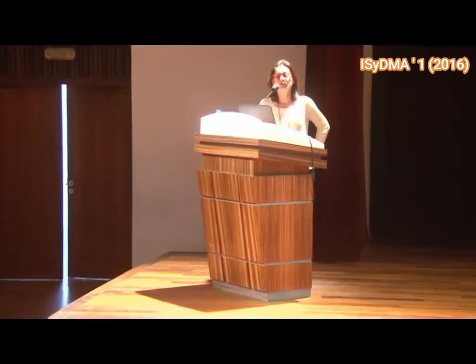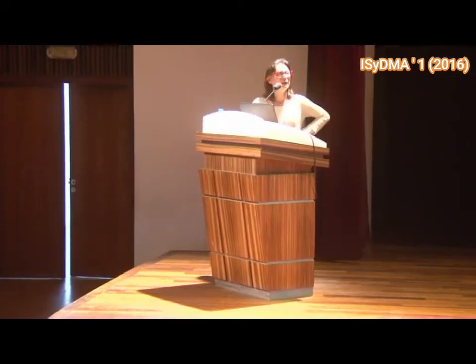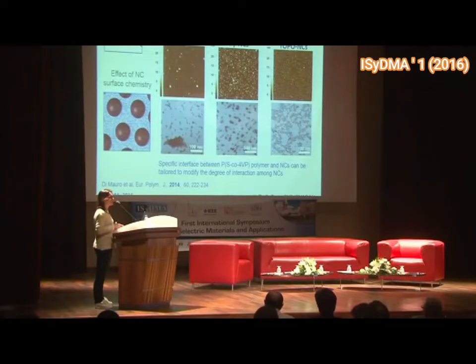Another approach is the common solvent method, in this case with red-emitting quantum dots. From the luminescence spectra, we can see that the nanocomposite retains the emission properties of the nanocrystal, because the quantum dot came out from synthesis, as I said before, with this TOPO molecule that is insulating. But when you need charge transport, generally you use this kind of ligand, as one of the ligands is used the pyridine.